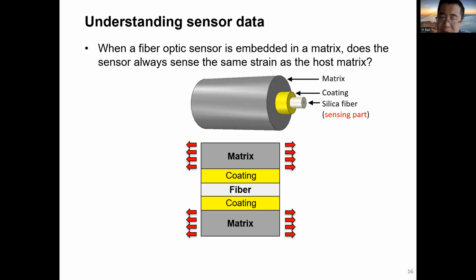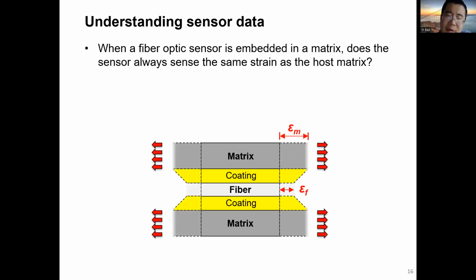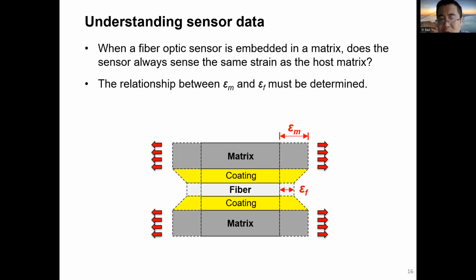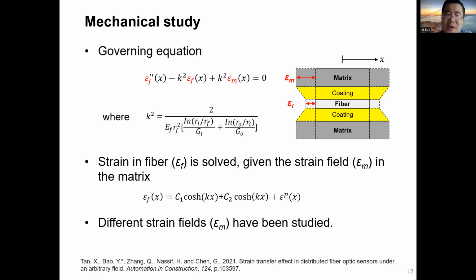So if we use the polymer coating, then are we measuring the real strain using the glass fiber? In fact, there is a shear deformation in the polymer coating, right? Because of this shear deformation, the strain sensed by the glass fiber will be different from the real strain in the host matrix, like a concrete matrix. This is known as the strain transfer effect. This effect has been well studied for point sensors. Point sensors can be considered as very short length. Within its length, the strain field in the host matrix can be considered as constant strain. Well, this problem can be solved through a mechanical analysis.